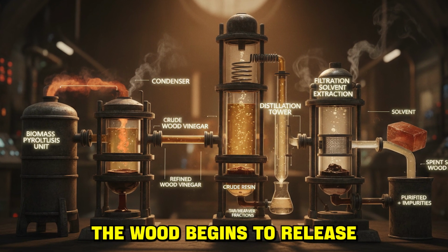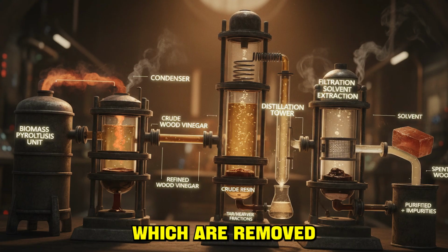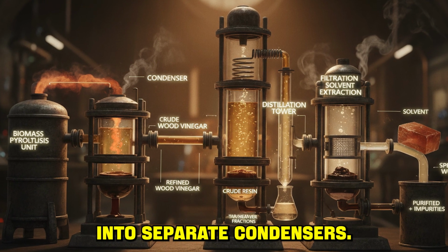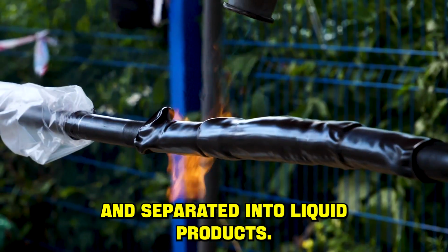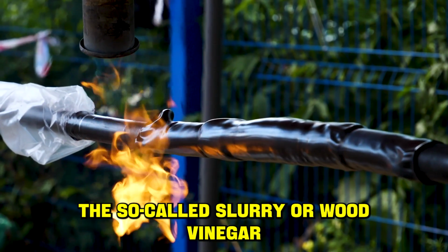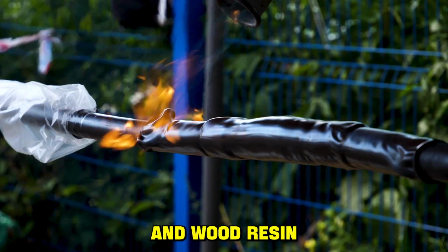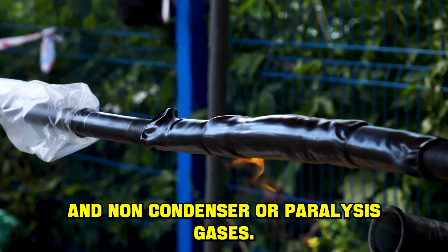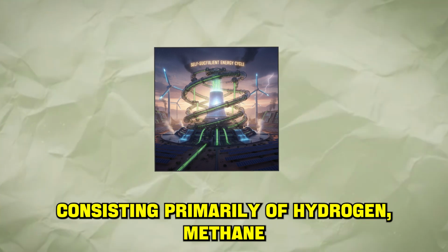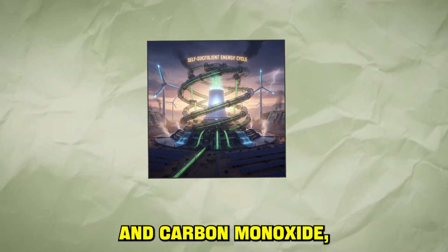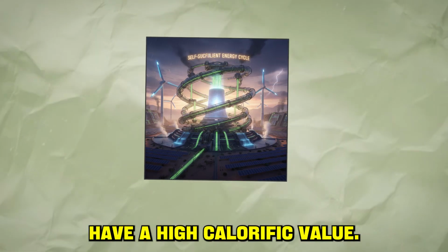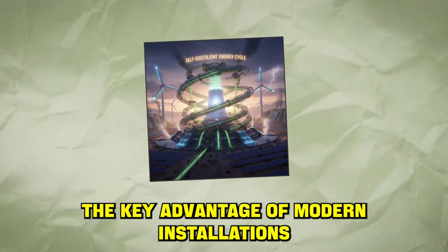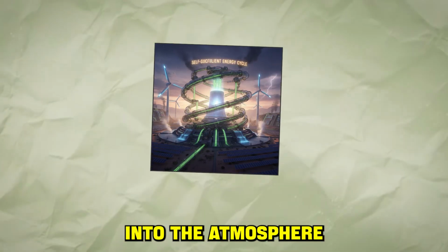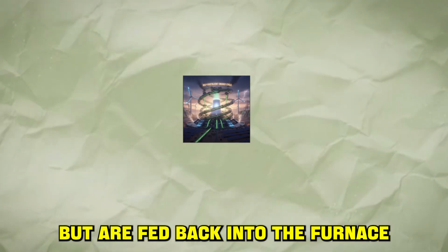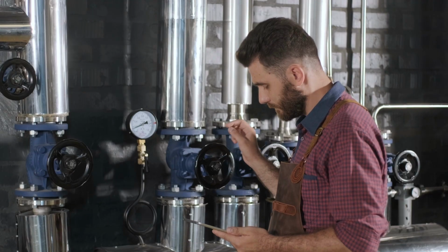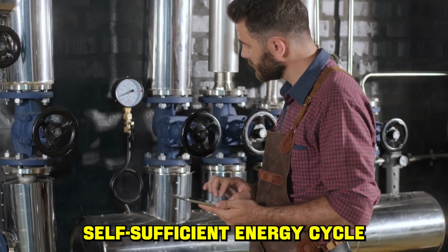As it heats, the wood begins to release volatile substances, which are removed through a system of pipes into separate condensers. Here, they are cooled and separated into liquid products, the so-called slurry, or wood vinegar, and wood resin, and non-condensable pyrolysis gases. These gases, consisting primarily of hydrogen, methane, and carbon monoxide, have a high calorific value. The key advantage of modern installations is that these gases are not released into the atmosphere, but are fed back into the furnace to maintain the pyrolysis process, creating a virtually self-sufficient energy cycle.